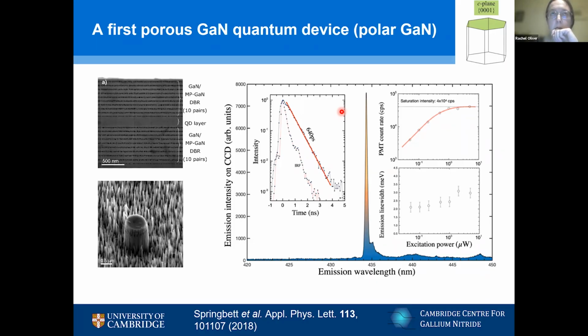So we think that if you have an indium nitrogen chain, so just two indium atoms happening to be next to each other in a quantum well, that will localize the hole. My overall picture, and this is borne out by some of Stefan Schulz's atomistic simulations, is that you've got your quantum dot and somewhere within it there is your high indium content region, almost the core of the dot, and that's really where at least the hole is localized. That's a slightly different picture than the continuum models I've been showing so far. But it does mean that the whole thing is quite robust to the compositional fluctuations, because there'll just be some high indium point within the dot, which is the most localized state, and the carriers tend to end up there. I see, thank you.